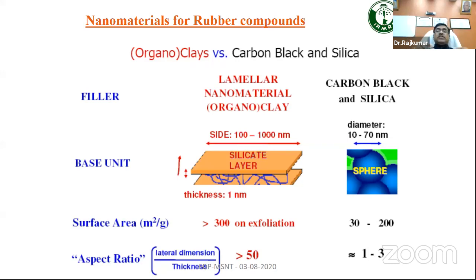Here basically the thickness is 1 nanometer. So the silicate layer is a layer, whereas the other is spherical, and the surface area is more than 300 on exfoliation, whereas here it is 30 to 200 basically. So aspect ratio is lateral dimension divided by thickness, basically 50, whereas here it is 1 to 3.